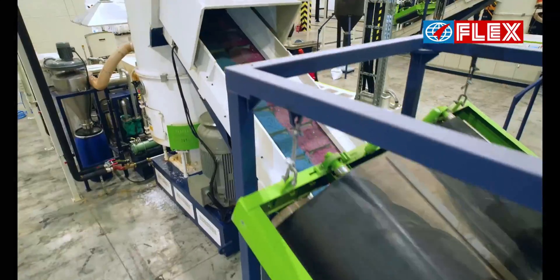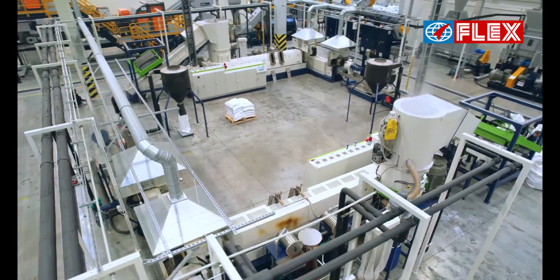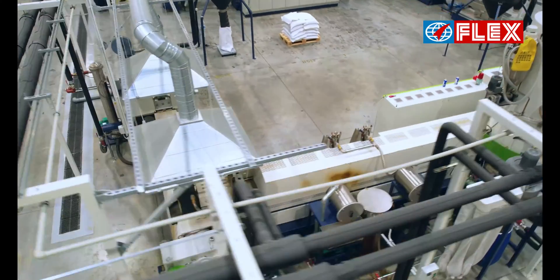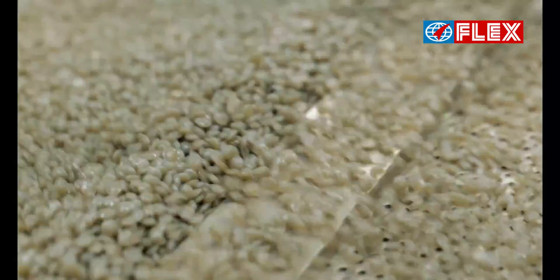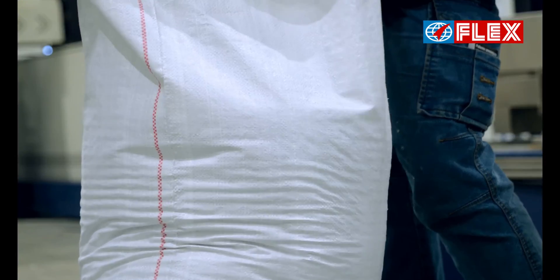The washed and shredded material is dried and compacted into mixed plastic agglomerates. The agglomerates are processed through a twin extrusion process where volatiles are degassed and compatibilized to ensure a homogeneous extrudate. A customized underwater die-face cutter ensures uniformity in the size of granulates.